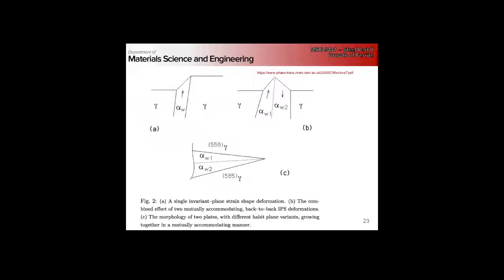The system can reduce this by not just nucleating one Widmanstatten orientation, but another one with the shear in the opposite direction. So as these two grow, the overall effect of them is canceled out, and we just get this offset right in the center. So they look like a triangle growing out, but they're not really one orientation - this is two Widmanstatten needles that come together, and they have their plane strain shear in the opposite sense.